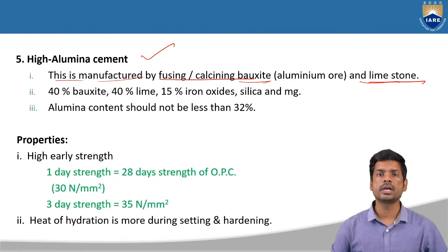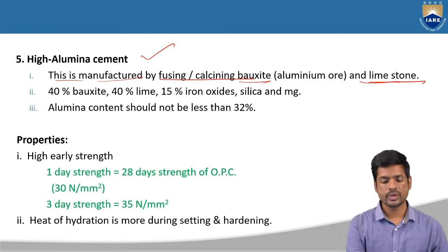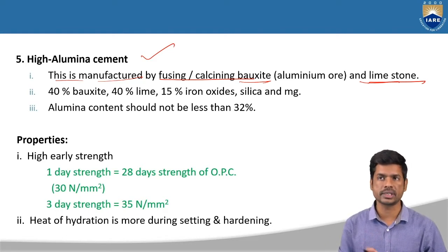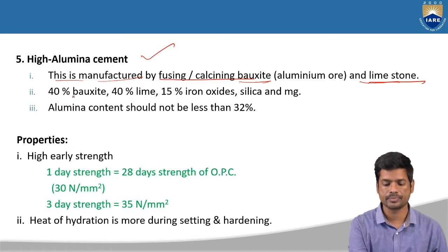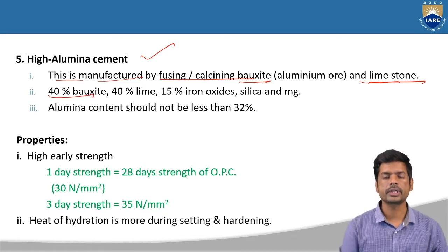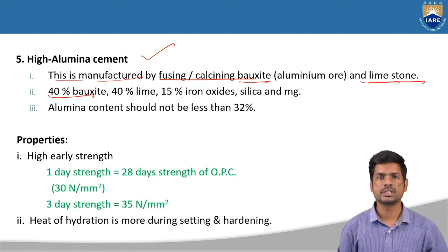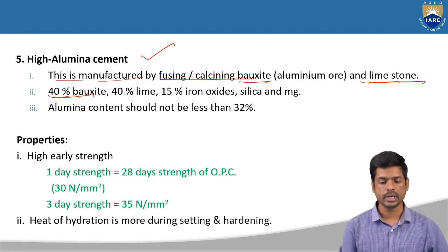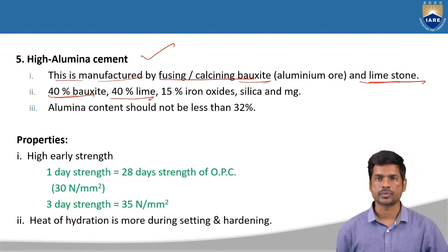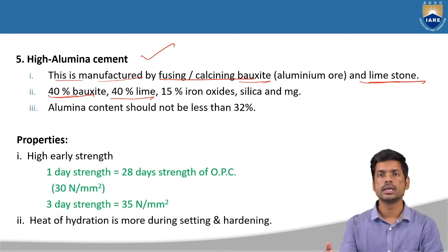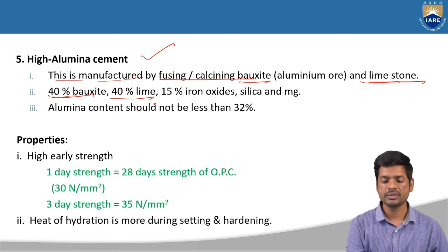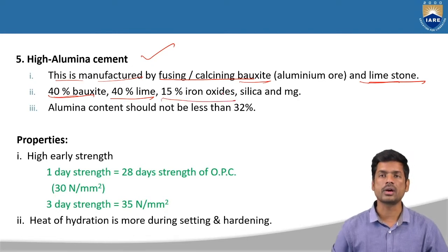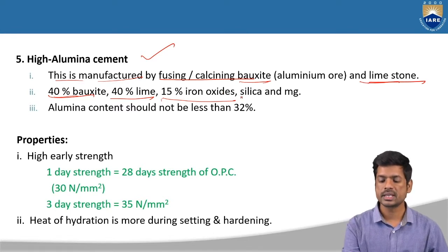Coming to the chemical composition of this high alumina cement, we have to maintain proper proportions of each and every element. Out of 100% of cement, we use bauxite around 40%, and the next 40% is lime. The remaining 15% is iron oxides, and the remaining 5% is silica and magnesium.